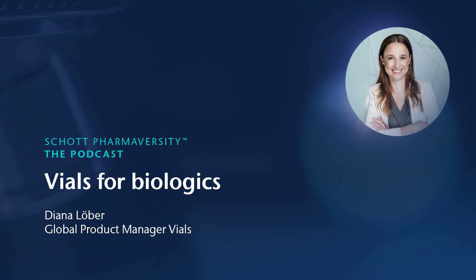Okay, so you've talked before about the PICVD process. Is this also used for these Type 1 plus vials you're mentioning? Yes. PICVD is also used for Type 1 plus vials. PICVD stands for plasma impulse chemical vapor deposition. It is a SCHOTT patented technique, and its uniqueness is that it ensures a covalent bond between the coating and the glass substrate. And this differentiates it from the other solutions used as barriers. A covalent bond means a bond on an atomic basis, and that's the strongest chemical bond achievable.